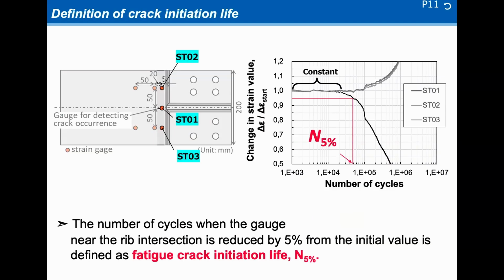Before the results, I'll explain the definition of crack initiation life. This chart shows the strain measured by the strain gauges near the rib-to-deck welded joints. The strain remains a constant value at the beginning, but the strain changes rapidly after a certain number of cycles. We think that the fatigue cracks initiated at this number of cycles. So the number of cycles when the gauge near the rib intersection is reduced by 5% from the initial value is defined as the fatigue crack initiation life.